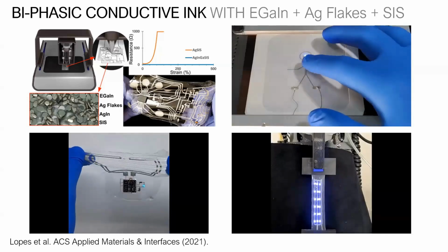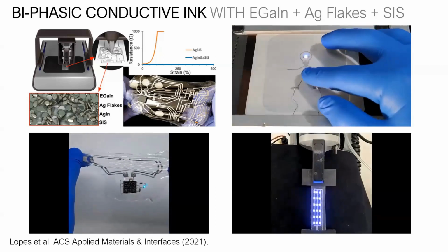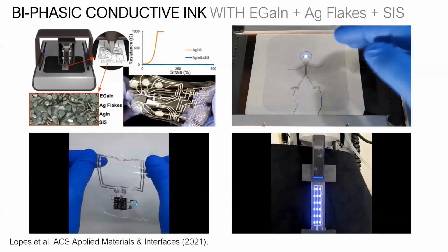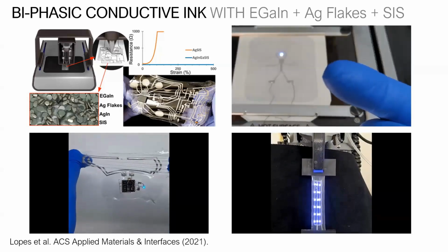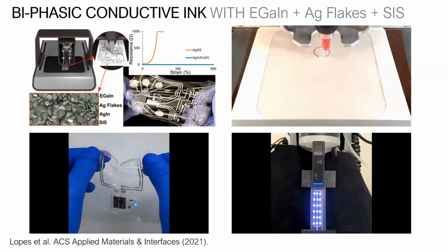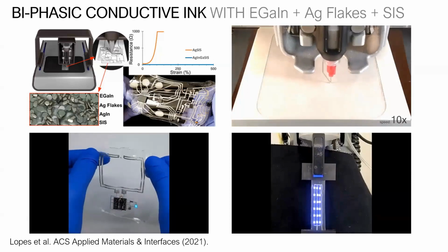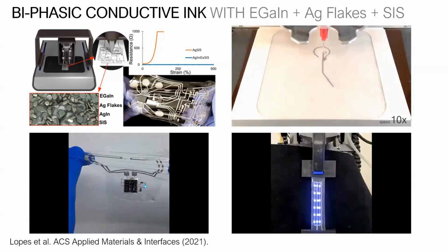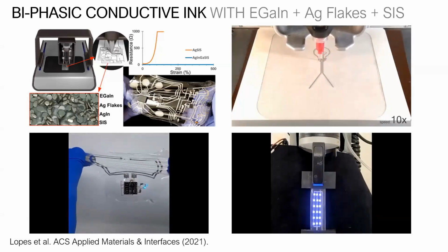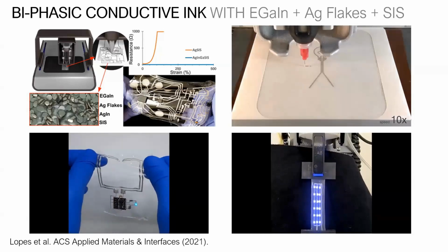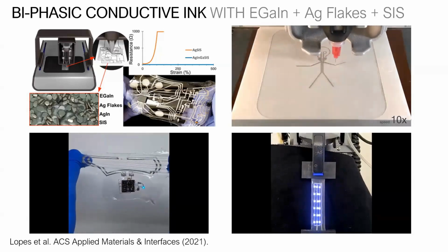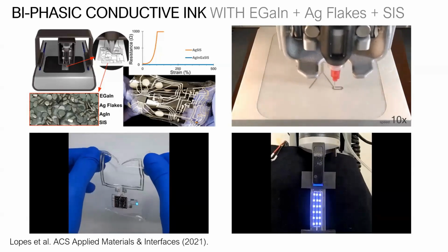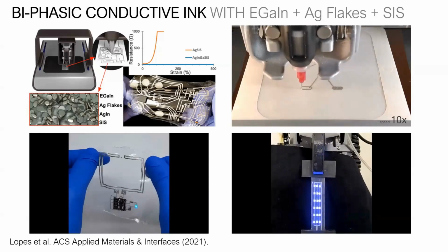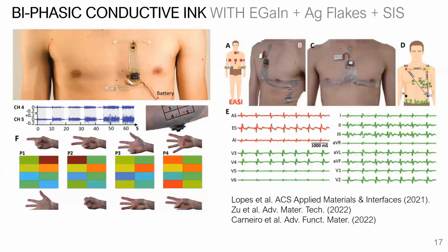Unlike just silver flakes and polymer alone, we have a fairly low concentration of these rigid filler particles, so we can maintain a pretty low viscosity, and then in the cured state we can have something that's quite rubbery and stretchable. And again, because of the microstructure, we have something that is quite stable under a stretch, and so the resistance doesn't really increase.